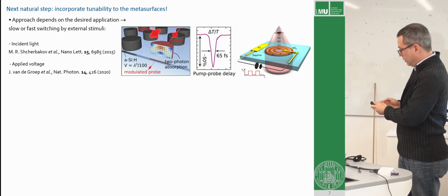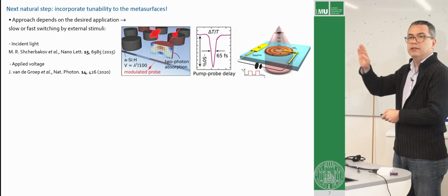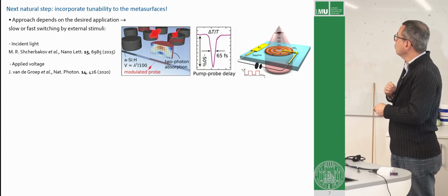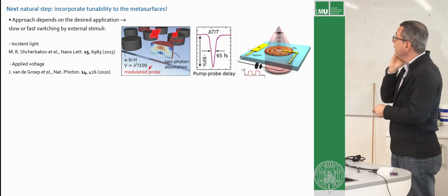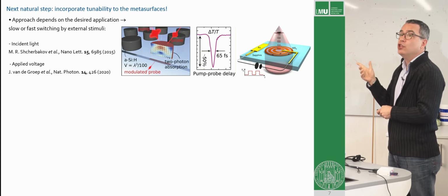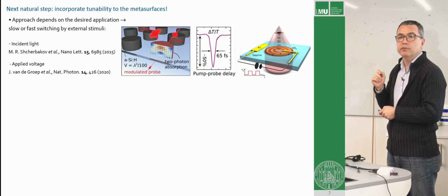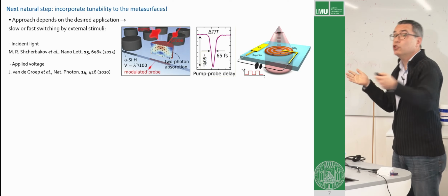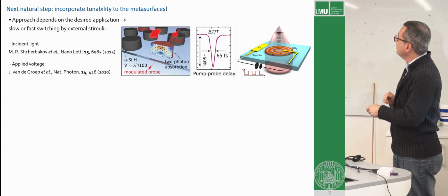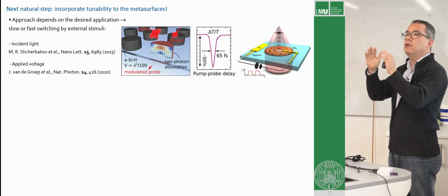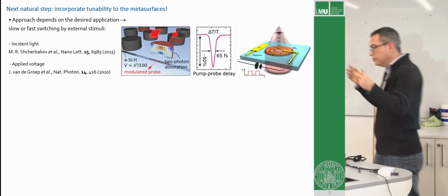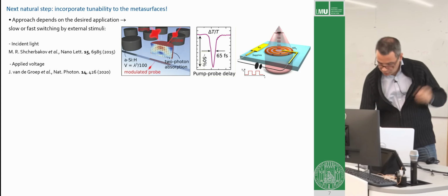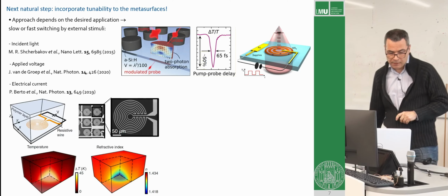And doing this, changing the position of the excitonic resonance in relation to the wavelength that you are illuminating this metasurface with, you change the imaginary part of the refractive index, and then you change the refractive index in the end. And then you can also change the way you're focusing light with this kind of advanced Fresnel lens, although it's not exactly a Fresnel lens.